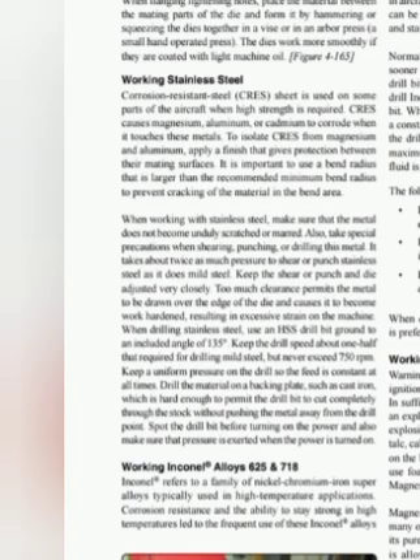It takes about twice as much pressure to shear or punch stainless steel as it does mild steel. Keep the shear or punch and die adjusted very closely. Too much clearance permits the metal to be drawn over the edge of the die and causes it to become work hardened, resulting in excessive strain on the machine.